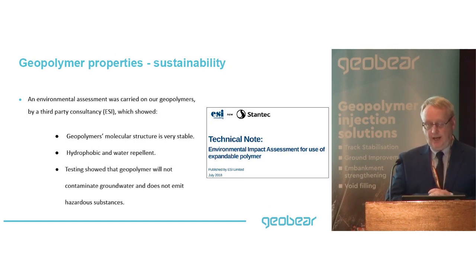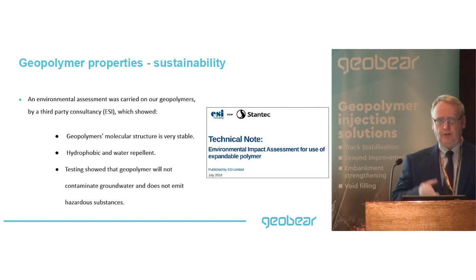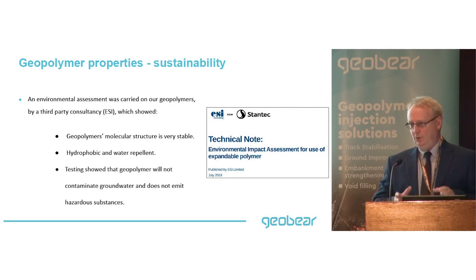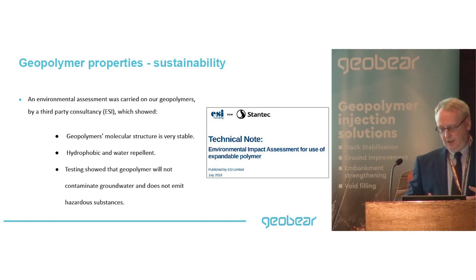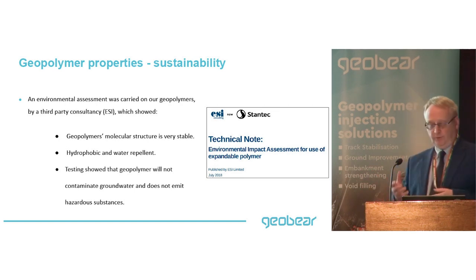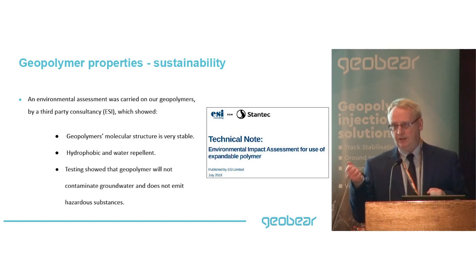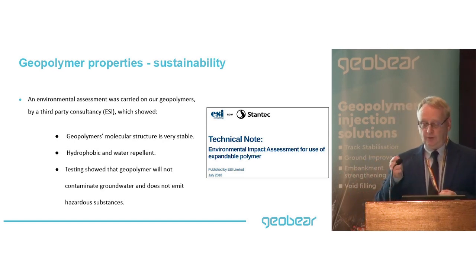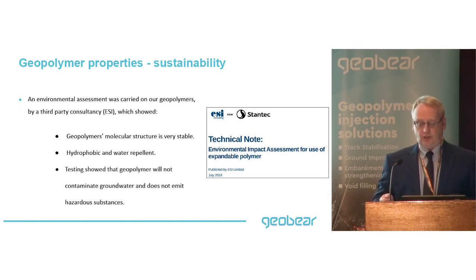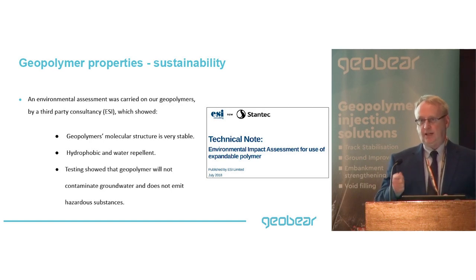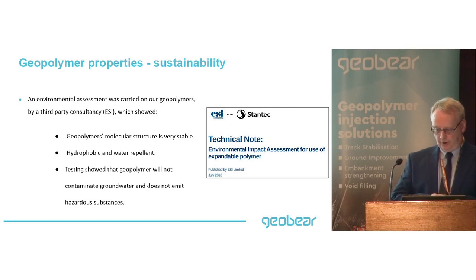We've had them tested extensively, because it's very important that if you're injecting chemicals into the ground, you're not going to contaminate groundwater or generate a leachate problem. We've crushed the material up into fine sand-sized particles and done leachate testing, and we've not detected any harmful chemicals above laboratory detection limits in the leachate. So we're very confident that they're safe to use over aquifers, and we've never had a problem reported in terms of the impact on the environment. They're environmentally friendly products.